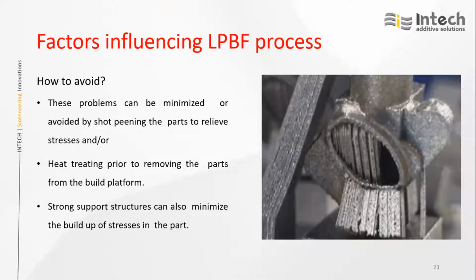So a kind of shot peening or roughing is required. Then heat treatment to relieve the stresses before we actually break the supports. Supports are supporting structures. If stresses are not relieved and you remove the supports, there will be a chance of distortion in the component. This needs to be minimized or eliminated. To eliminate that, we need to relieve the stresses.